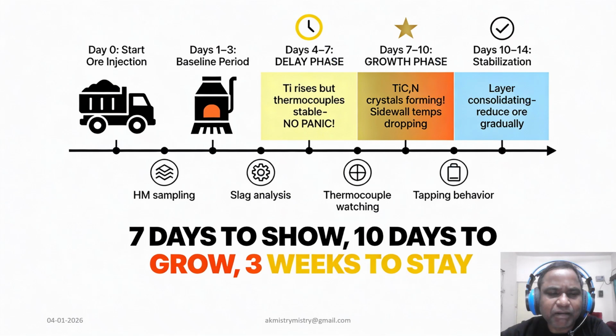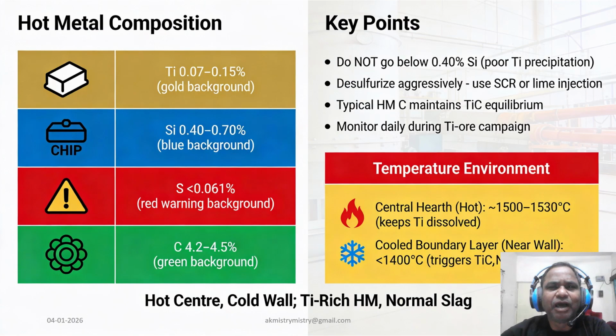Now timing is everything, as it is our tagline for this activity. Our mantra is 7 days to show, 10 days to grow, and 3 weeks to stay. During the first week you will see titanium level rise, but thermocouple might stay stable. Don't panic. By day 10 the growth phase begins and crystals form, and you will see sidewall temperature finally start to drop. To maintain this reaction, we need a hot center and cold wall.